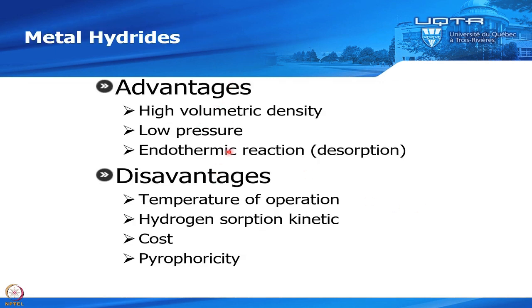So the advantages and the disadvantages. For metal hydride, the advantage, as we said, is high volumetric density. It could work at low pressure. But the reaction of desorption is endothermic. Why I list it as an advantage is because if you have a metal hydride tank in your car and you have an accident and the tank is ruptured and you have hydrogen getting out and hydrogen is taking fire, then it will heat up the tank. But as the tank is heating up, it will desorb hydrogen. And as it desorbs hydrogen, because the reaction is endothermic, it will have a tendency to cool itself. So it will kill the reaction by itself. So this is inherently safe.